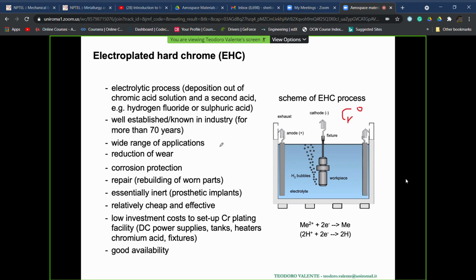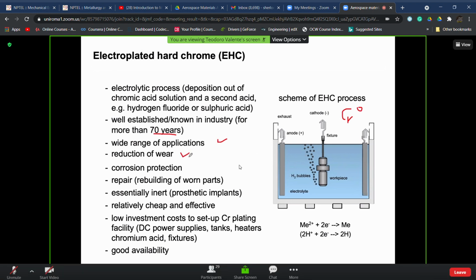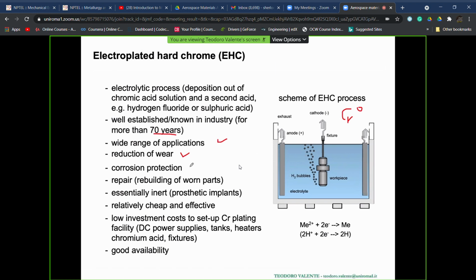This system has a wide range of application, is very well known, used in many industrial fields since about 100 years. It is able to give us very hard coatings, just reducing wear. In some cases, that depends, also giving a corrosion protection. It is cheap and effective, and the system itself requires a low investment cost if compared, for example, with the HVOF. So that has been, and sometimes it is still used, let me say, the standard solution for fabrication of highly resistant coatings for wear problems.